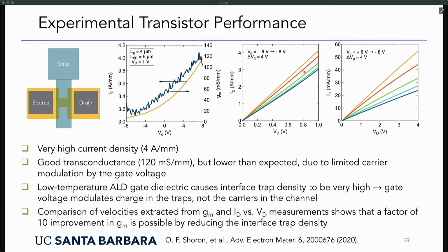The current modulation is moderate, and this is largely due to the fact that we still have carriers in the bulk that are not responding as well to the gate voltage. But the other big problem, and this is some separate study that I cannot show you because of time constraints, is interface trap density between the gate dielectric, which is aluminum oxide deposited by ALD in this case. These interface traps are large. So the gate voltage largely modulates the trap density rather than the carriers in the channel, and that reduces the charge modulation in the channel, and that results in a reduced transconductance.